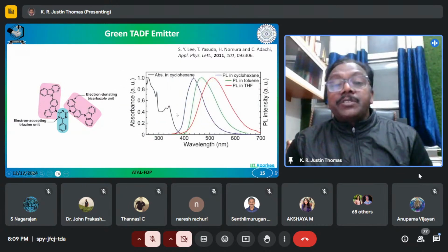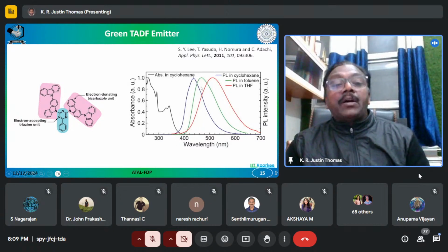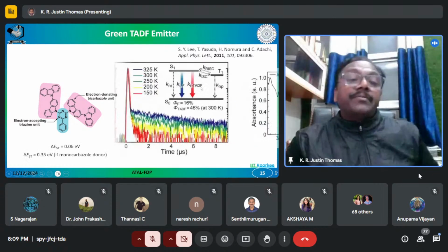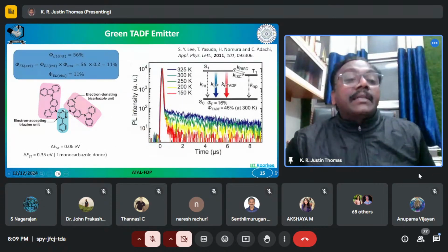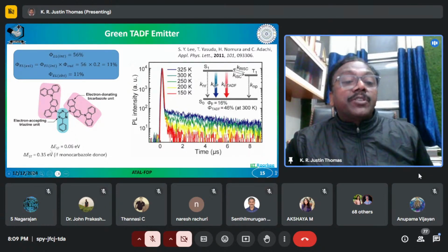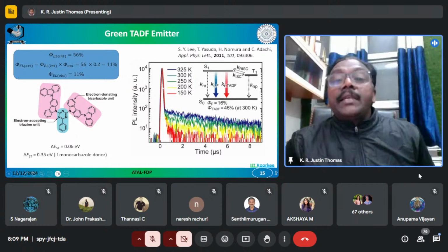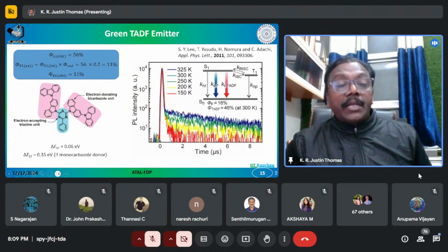And absorption without the charge transfer transition, and then the emission typical of a charge transfer excited state. And if you look here, as I have already told, the delta EST with a monocarbazole is 0.35, and the moment you put bicarbazole, the delta EST becomes very small. As I have already told, it will have 2 lifetimes, which is sensitive to the temperature as well, because it is a thermally assisted process.